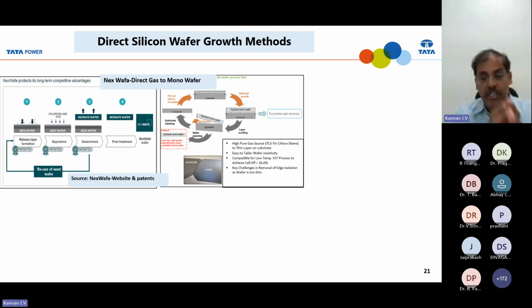Okay. So in addition to the crystalline silicon, there are some methods where you can use the gas phase. Instead of using polysilicon, you melt it and grow in a square shape or cylindrical shape, then cut it. So many different processes. So there are industries also trying to grow the wafer shape through gases. Directly you can deposit on some substrate, then you take out that top, cleave that top deposited surface, so that you can use that as a wafer.